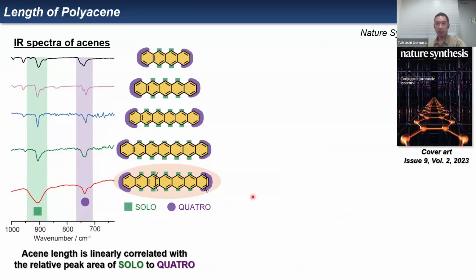So now let's check the length of the polyacene. The polyacene is insoluble in any solvent and cannot be volatilized. So we couldn't estimate the length using conventional methods such as GPC and MALDI mass spectroscopy, and we also can't use microscopy. But instead, we use IR because this is also a quantitative analytical technique. Here we focus on the intensity of this solo and the quattro peaks because this is the repeating group and this is the terminal group. And we found that the acene length is linearly correlated with the relative peak area of these solo to quattro mode peaks.